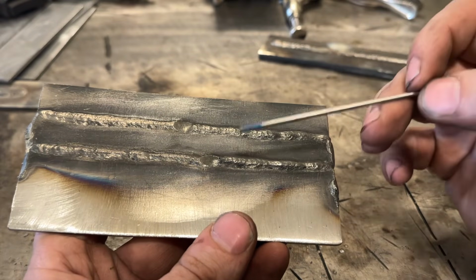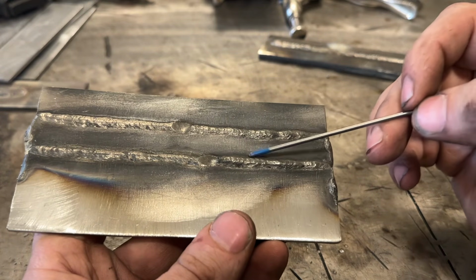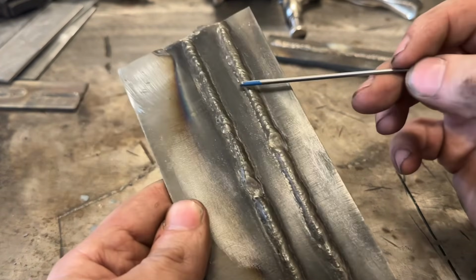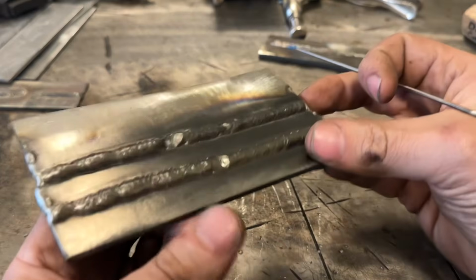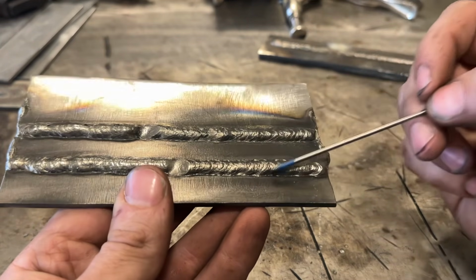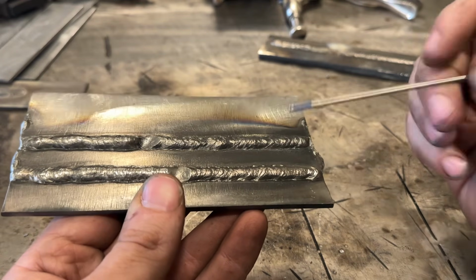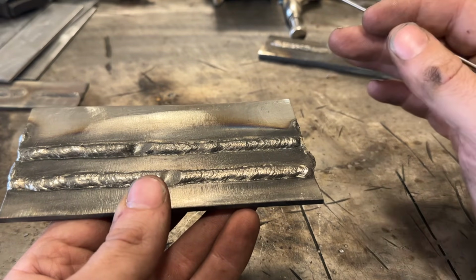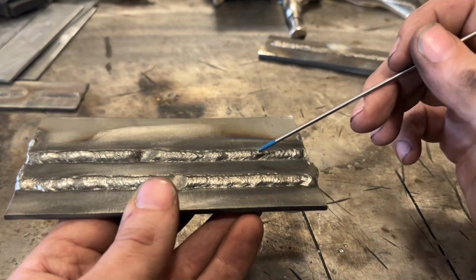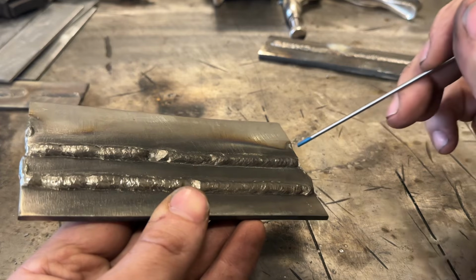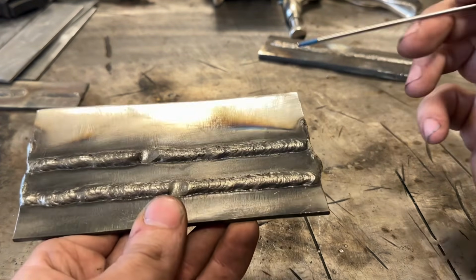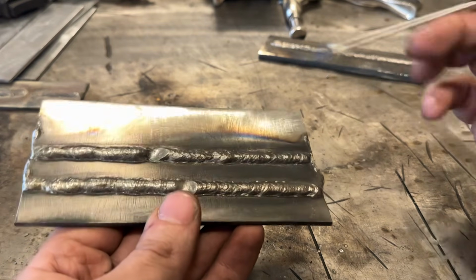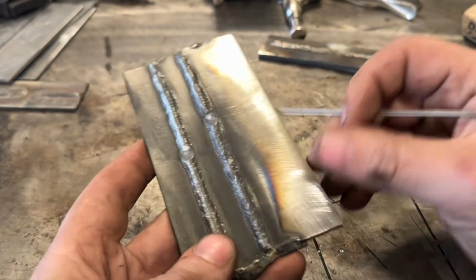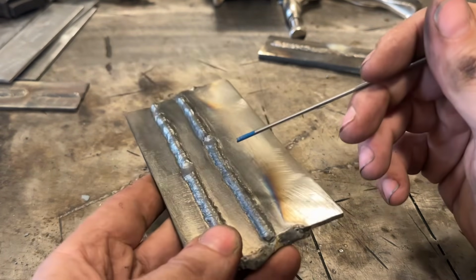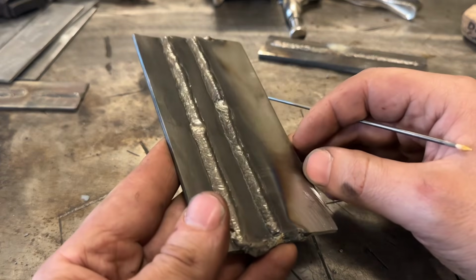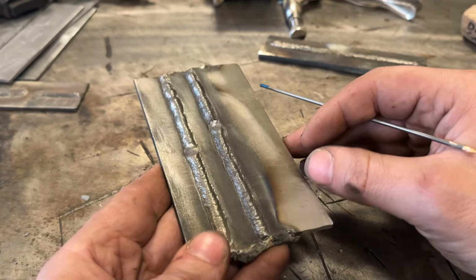So by cutting the wire down to deposit an appropriate amount of metal, that allowed us to get closer to where we should be. Now, like I said, there's definitely some more tweaks we can do, but at this point I'm pretty confident saying it's just a matter of plus or minus 0.1, 0.2 volts and 5/10 on a wire feed speed. And really it comes down to a little bit of practice and a little bit more consistent movement. I haven't done vertical up on flux core with .035 in a very long time. Like I said, I always use .030, so I'm actually pretty happy with the results here. I'm thinking they're looking pretty good, all things considered.